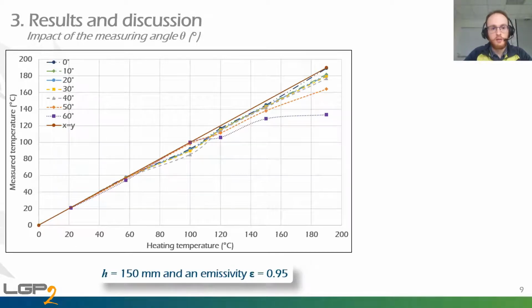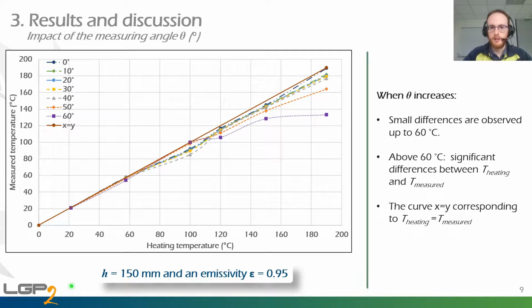Concerning the measuring angle, we will have here the same figures as before, but here h and the emissivity are fixed, and only theta will be changed between 0 degrees to 60 degrees. As you can see, when theta increases, small differences are observed up to 60 Celsius degrees. Nonetheless, above this value, significant differences between the heating temperatures and measured temperatures are observed.